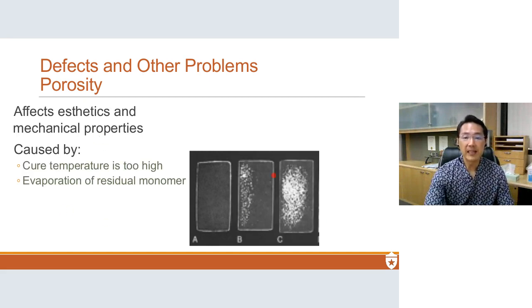B and C are when the cure temperature was too high, and so you get boiling or evaporation of residual monomer. If you have too much of that, you didn't cure it to completion, and you had a lot of monomer left over that evaporated, and you get this kind of porosity happening throughout the material.